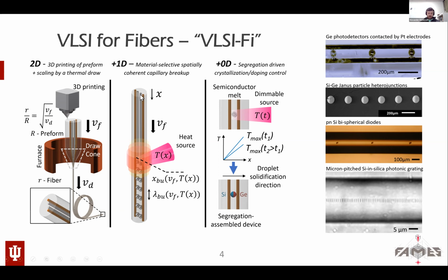And those semiconducting cores are p-n doped silicon. Okay, and you can reheat the fiber locally by a hydrogen oxygen flame or by a laser spot, such that a short section of semiconducting cores is liquid, and then feed the fiber through that hotspot.